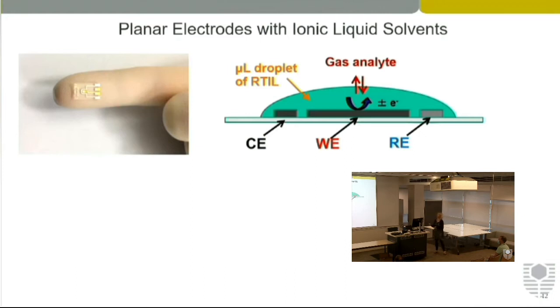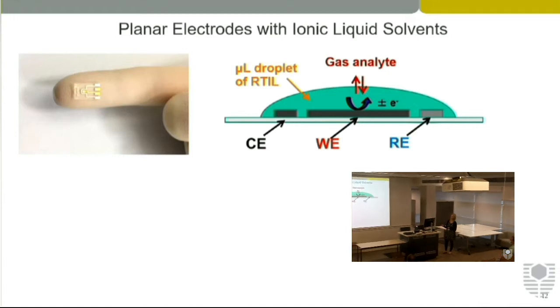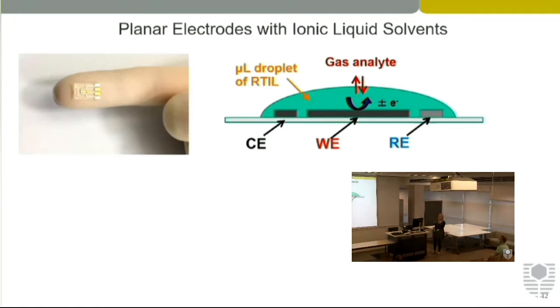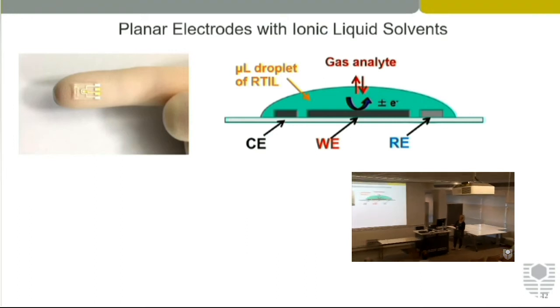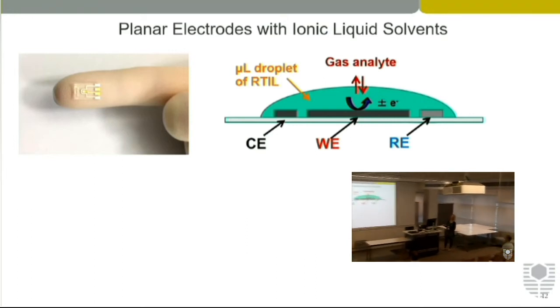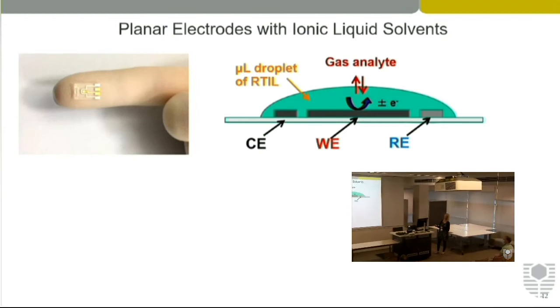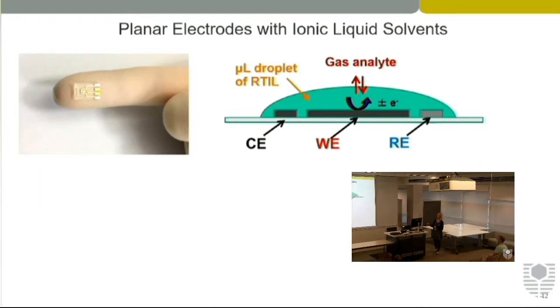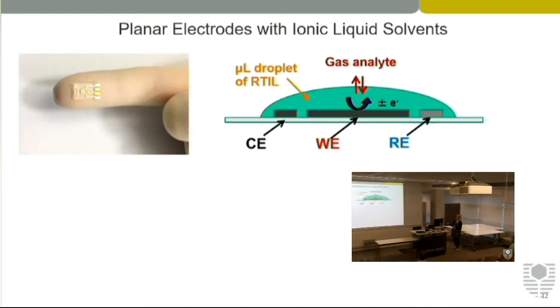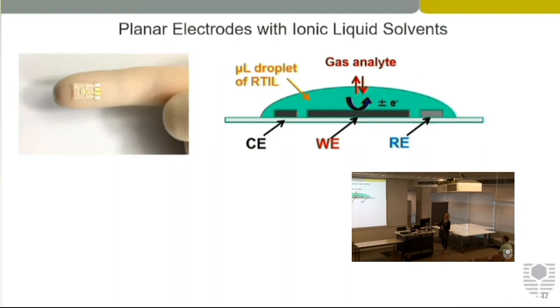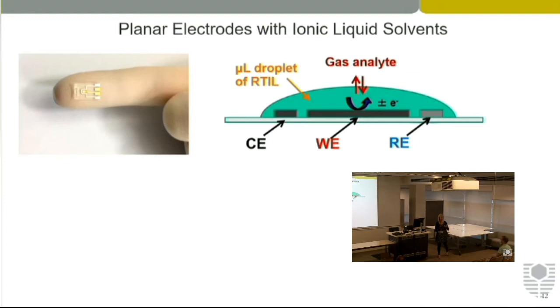So here is a closer up image of our design. These are commercially available devices, about $5 a unit, so much cheaper than the commercial sensors. They have very thin layers of pure metal. This is a gold working electrode in the middle, surrounded by a platinum counter and reference. Looking at the side of this planar device, you'd have the metals deposited onto the glass substrate, and then we drop a microliter droplet of ionic liquid. We can get away with about 0.5 microliters, so really small volumes.